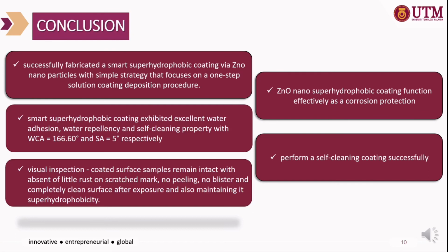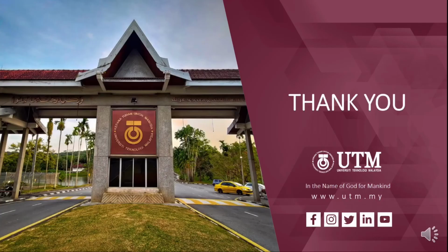This shows that the zinc oxide nano superhydrophobic coating functions effectively as corrosion protection and also performs as a self-cleaning coating surface successfully. I believe that a superhydrophobic surface created by a simple, cost-effective, scalable, and easy approach is a good candidate for usage as a self-cleaning coating in a wide variety of applications due to its significant corrosion resistance and simple fabrication and composition.